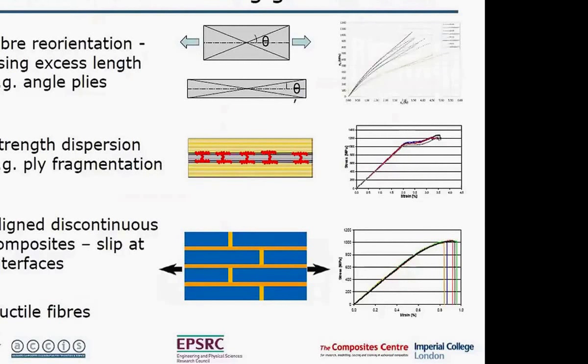The second mechanism is by using strength dispersion, getting actual failure within the material, and one of the mechanisms there is ply fragmentation, and that I'm going to talk about extensively over the next half an hour. We can also generate additional strain by having discontinuous fibers, aligned discontinuous composites, where we get slip at interfaces. That again can yield additional strain, and we've done quite a bit of work on that. But again, I'm not going to cover that this morning.